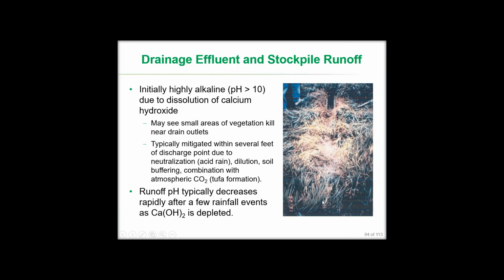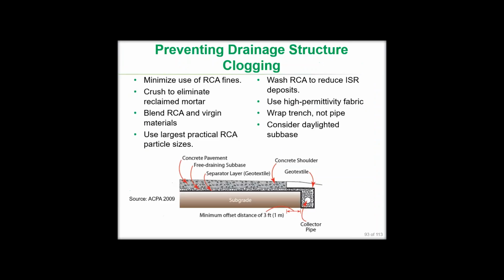Typically you got beyond that, and between issues of neutralization with the rainfall that's happening in those areas, and you get a little bit of an acidic rain, along with just general dilution with the other waters that are flowing through the area, soil buffering, other sorts of things, you never saw this extend much beyond the region of the head wall outlet. And usually you didn't see it for very long after the pavement was placed, because after that calcium hydroxide is removed and dissolved off the surface of those particles, then there's nothing left to flow out, and you have a normal flow of material. So it's a relatively temporary effect, but it is still a real effect.